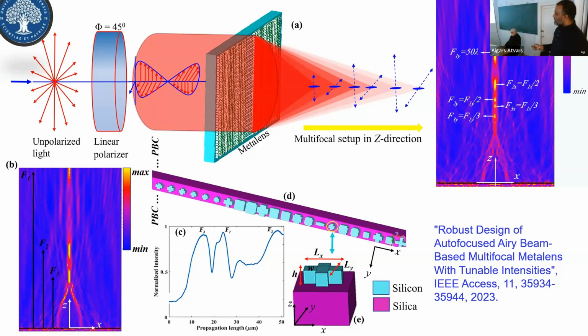You can see the experimental result over here. This is the result we obtained. Here you can see there are 1, 2, 3, 4, 5, 6. I was able to form 6 focal spots at different distances. 3 focal spots are formed by the X component of the incident light, and 3 focal spots are formed by the Y component of the incident light. And it has a very high efficiency. The diffraction efficiency of this metalens is 95%. Usually, you will not achieve 95% diffraction efficiency with a conventional diffractive optical lens. It is only possible if you use a metalens made up of metasurfaces and metamaterial atoms.